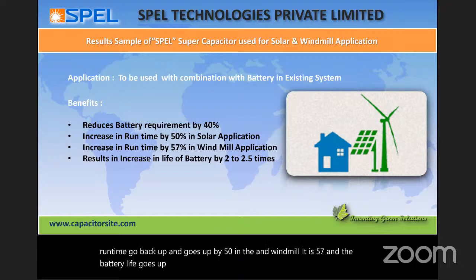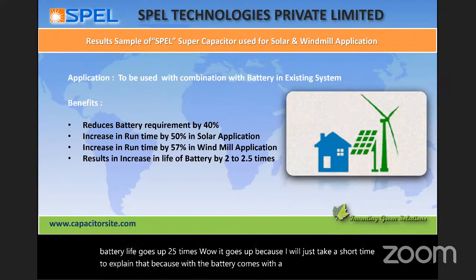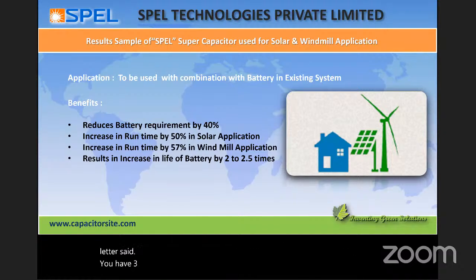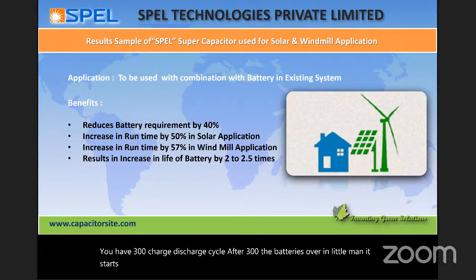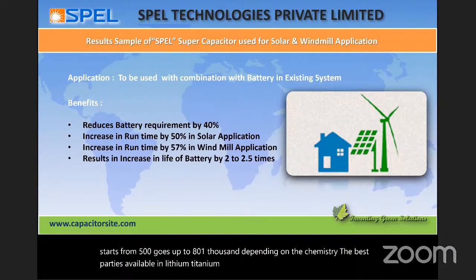How does it go up? I will just take a short time to explain that. Because the battery comes with a life tag. Like a lead acid battery, you have 300 charge discharge cycles. After 300, the battery is over. In lithium ion, it starts from 500, goes up to 800, 1000, depending on the chemistry. The best part is available in lithium titanium oxide, which is around 3000 plus.